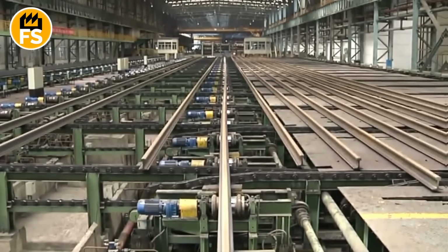After the steel comes out of those final rollers, it's moving along at about 18 miles per hour and still glowing at 1,650 degrees Fahrenheit. This next moment is probably the most critical 4 seconds in the entire process. Water jets blast the top surface of the rail at 800 pounds per square inch of pressure, and the temperature of that head section drops from 1,650 degrees down to 400 degrees in just 4 seconds flat.